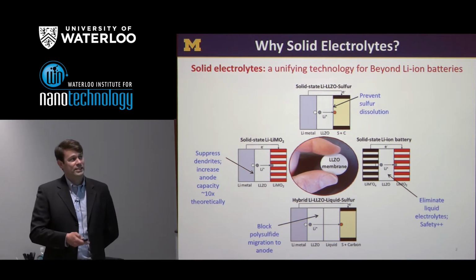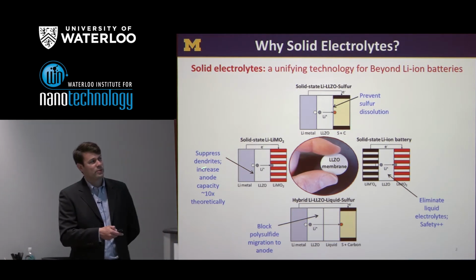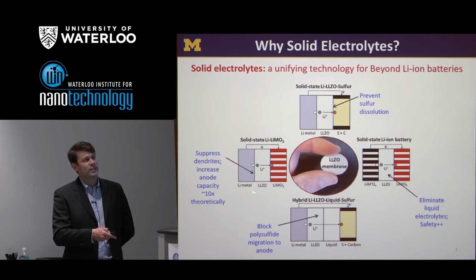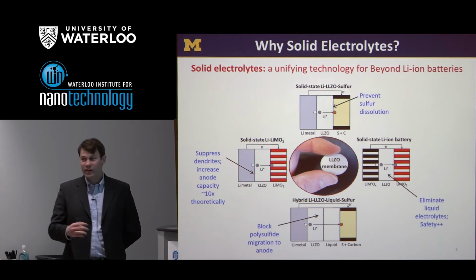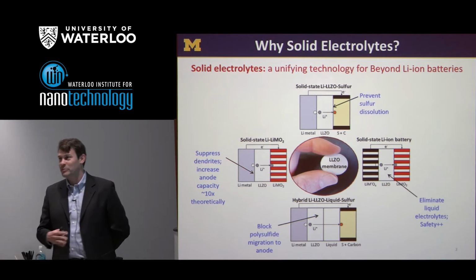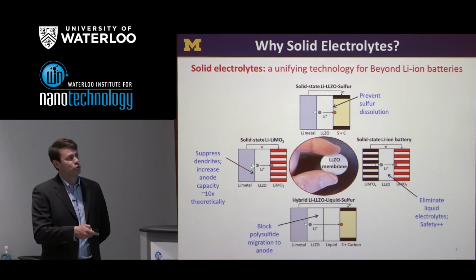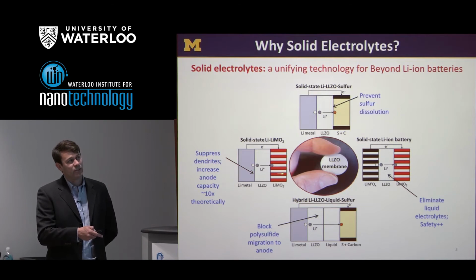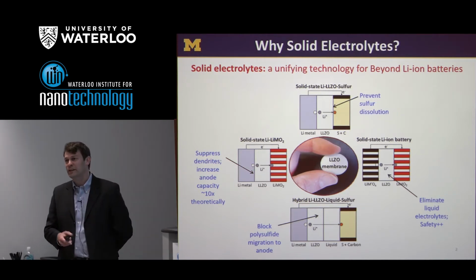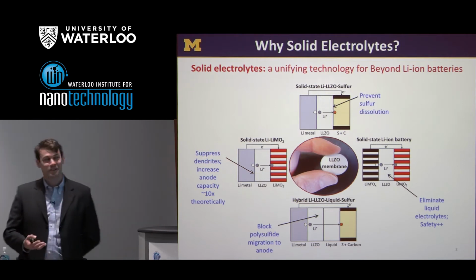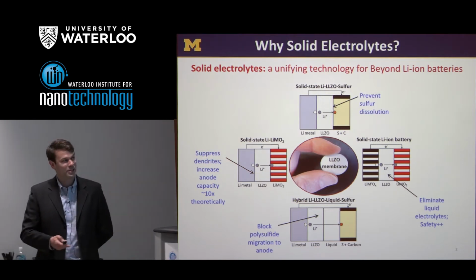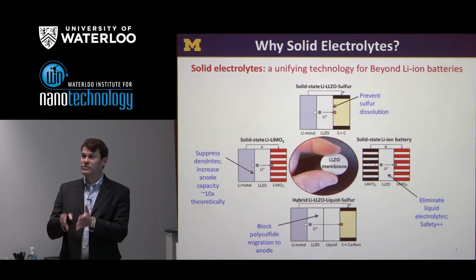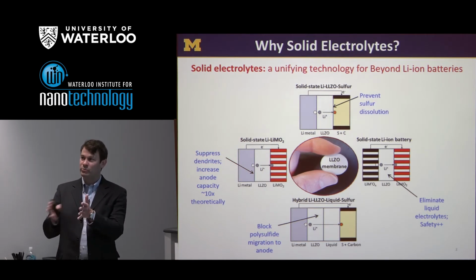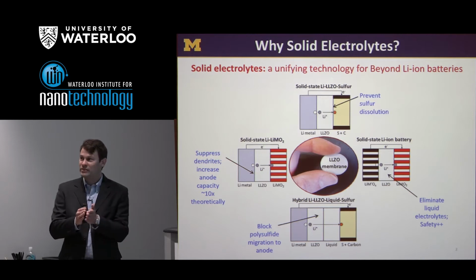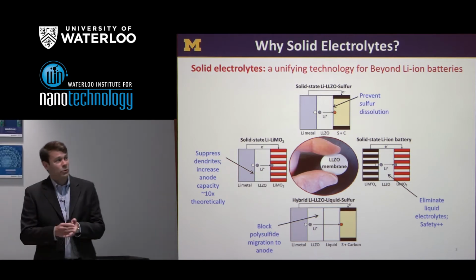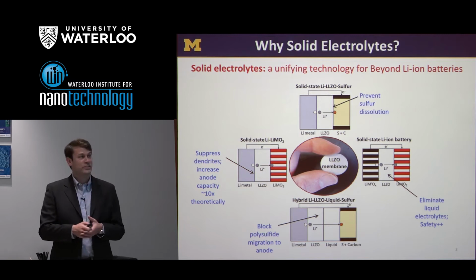So the reason we don't do that today is because of the so-called dendrite problem, which I mentioned here. If this again were a liquid and up against lithium metal, when we cycle that battery, the deposition and stripping of lithium ends up being non-uniform, and we develop protrusions that can cross the separator and form a short circuit between the negative and positive. So this leads to a very bad, you could say an explosive situation in a lithium metal battery. The conventional wisdom, however, is if we have a solid electrolyte, something that's very stiff, we can press that up against the lithium metal and prevent those lithium dendrites from growing. So we'll talk about the prospects of achieving that in a moment.